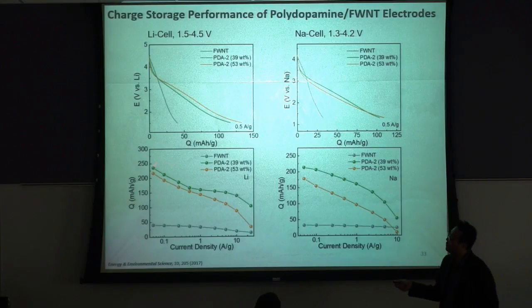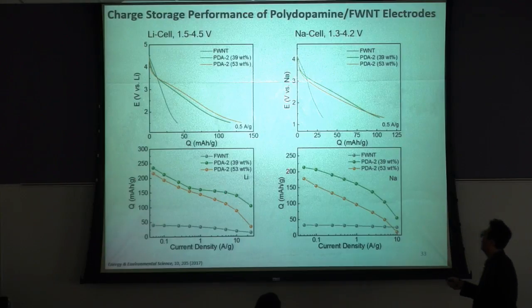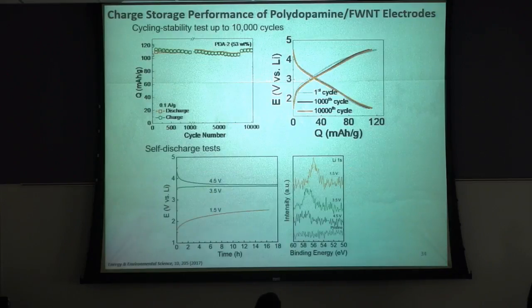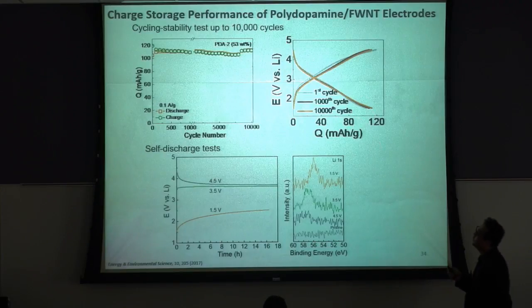So then if we estimate the capacity of only polydopamine, the capacity of only polydopamine is pretty high. It's over 200 milliampere hour per gram in lithium cell and also over 200 milliampere hour per gram in sodium cell. Also, it shows very good rate performance. And also, we did cycling tests, so we can see stable performance up to 10,000 cycles. So basically, there's no change of charging-discharging profile between the first cycle and 10,000 cycles.